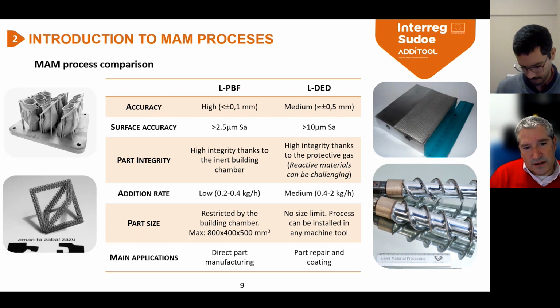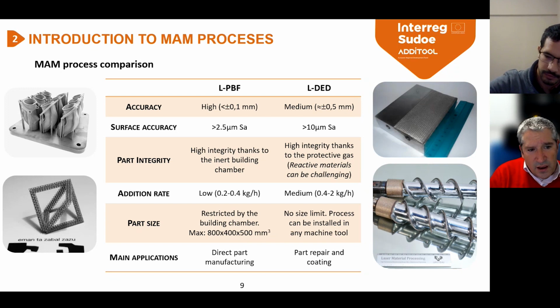And on the other hand, the laser direct energy deposition, in that case, we do not have so good quality in terms of surface finishing and tolerances. Here it is very difficult to obtain tolerances below 0.5 millimeters. 1 millimeter can be the process limit. Surface roughness is also not so good. So in this case, we will need almost 100% of the times to finish with further machining or grinding operations. We also obtain very good integrity in the parts, since we also introduce protective gas.